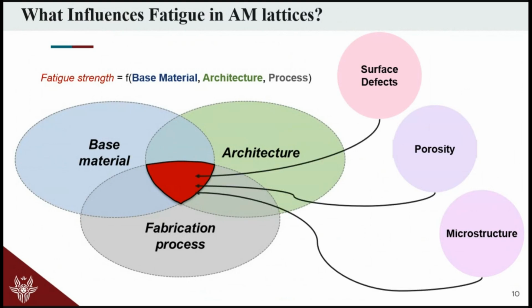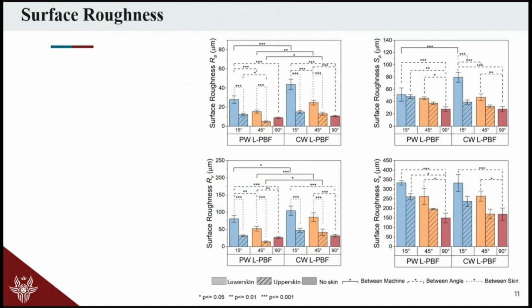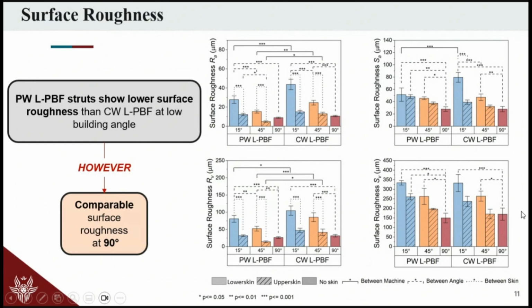the failure. So starting with a surface roughness analysis that has been done on both cases for all the building orientations, we have basically 2 parameters of interest, which are Ra and Rq, as well as Sa and Sq. And we can consistently see that there are statistically significant differences between the pulsed wave and continuous wave, particularly at inclined angles. However, when we are dealing with 90-degree specimens, we do not see any kind of statistical difference. This, if you remember the graphs before, suggests to us that probably surface roughness is not the driving mechanism that leads to the discrepancies in fatigue resistance in between the pulsed wave and the continuous wave laser powder bed fusion struts.